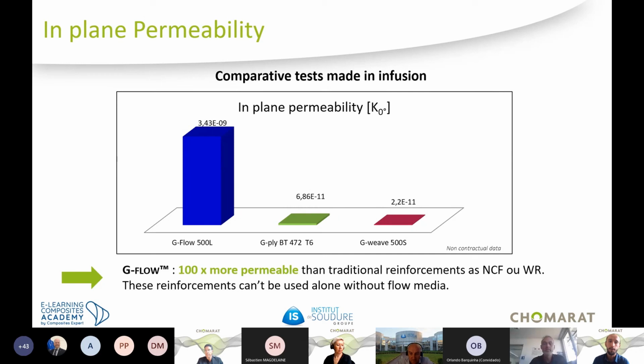portfolio. If we compare the 3 materials, which have all the same global constructions, fibers at 0 and 90 degrees, balanced in weight, we can see that the special weaving process of G-Flow allows for an in-plane permeability almost 100 times more than the other reinforcement. These reinforcements, such as NCF and woven fabrics, cannot be used alone in an infusion. That's why G-Flow has been developed, to allow for a full glass stacking to be properly infused and with high mechanical properties.